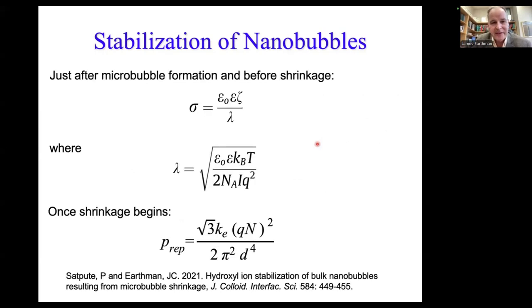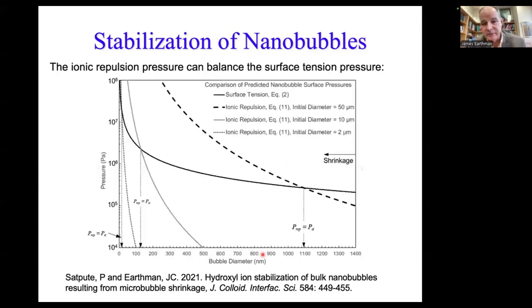And if you work through the math, I'll just skip to this last result because this is really the important result. I can go through these other equations if you like, but I just want to show you this result here at the bottom. That repulsion pressure goes up by 1 over the diameter of the bubble to the 4th power. Okay? So that means it's going to catch up with the surface tension pressure, because the surface tension pressure goes up by 1 over the diameter. So that was great. So we did some calculations, and lo and behold, you do get that this repulsion pressure will balance the surface tension pressure in the range of bubble sizes that were being observed for nanobubbles.